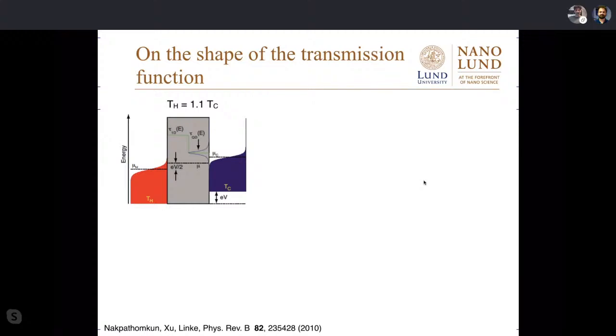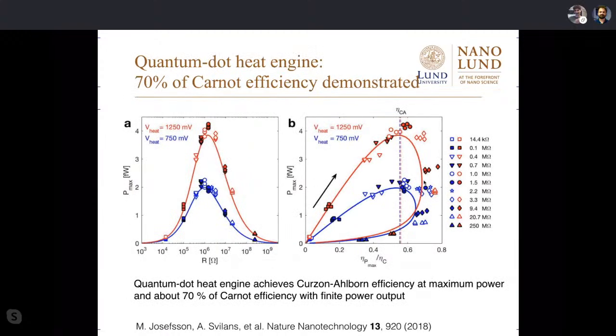A little comment here: because of this work and others, quantum dots are often seen as the optimal system for thermal to electric conversion. But there are a number of things one needs to say about this. One is we optimized the coupling to the reservoir such that we would get a decent signal, so we couldn't have too low coupling, but still as low as we could to get this delta function like resonance. And that allows us to get relatively high efficiency.